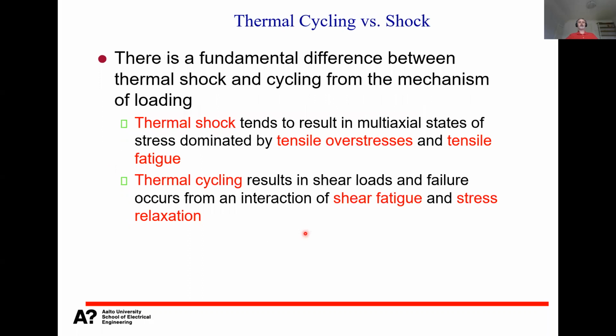Why this is important is that in thermal shock, we get more warping of the structures. So we can not only get shear stressing like in thermal cycling, but because of the warping, we also get tensile stresses. Tensile stresses are more severe for crack propagation. That's the reason we need to understand the difference between shock and cycling, from the use environment point of view, but also from the testing point of view.